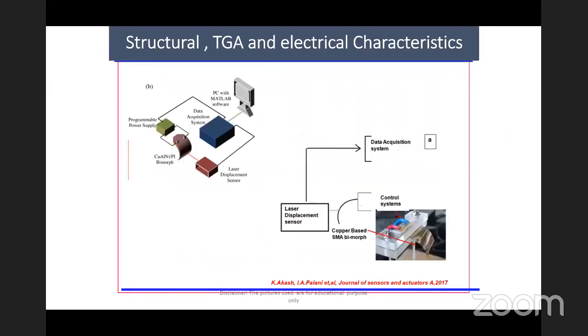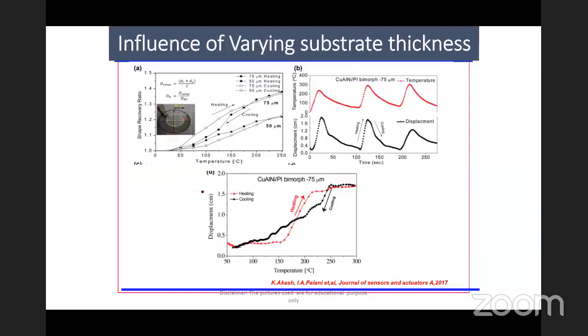So we made our own setup to study the life cycle of it. For that, we had a small fixture with a programmable power supply, in which we used the CuAlNi bimorph, and this is a laser displacement sensor, and this is the data acquisition system. The laser from the displacement sensor was falling on the CuAlNi bimorph, and we were continuously actuating it. Basically, we were giving a pulsed signal to it. So when we give a pulsed signal, there was opening and closing, finally ending up in proper actuation. In fact, this is the kind of life cycle we could achieve from it.